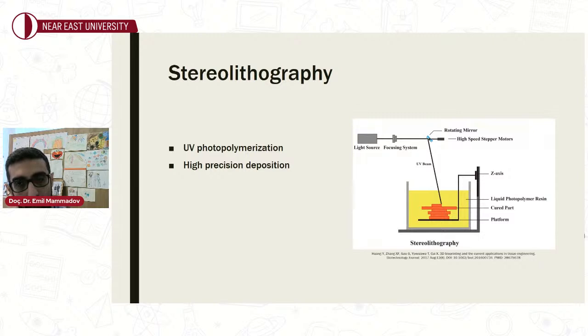There are two main disadvantages of this method. There are only two or three photosensitive biocompatible materials that we can use here, which are gelatin methacrylate and PEGDA, polyethylene glycol diacrylate. So material scarcity is the main disadvantage of this method, and curing the material with UV may also negatively impact the viability of the cells. However, some studies show that even this method may maintain high viability of the cells if used with appropriate UV doses.